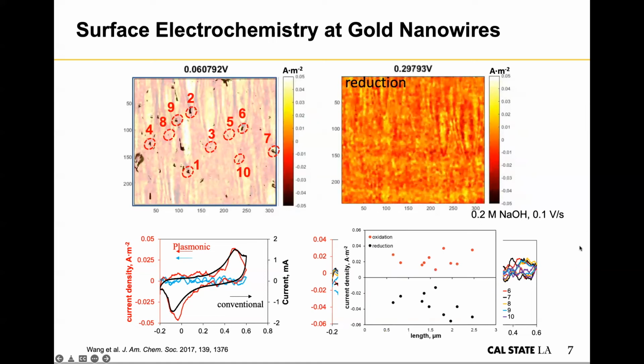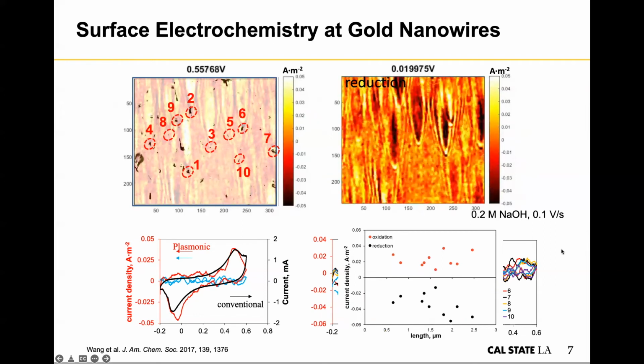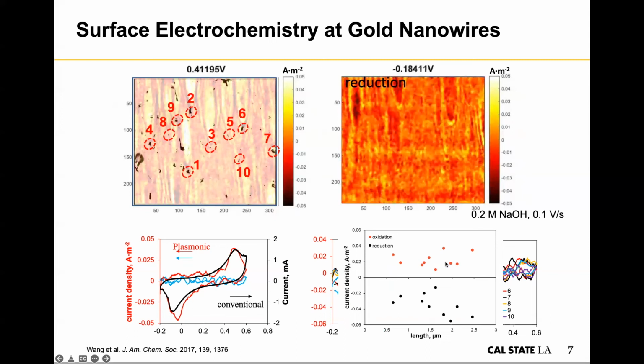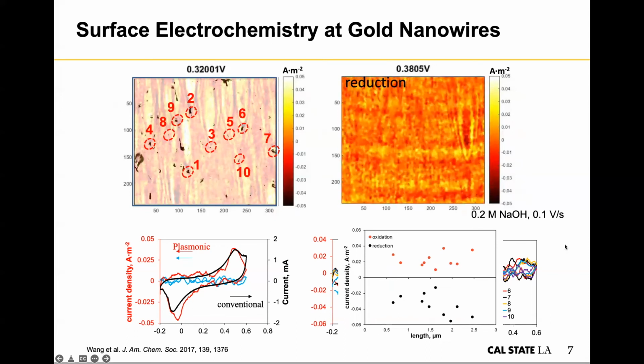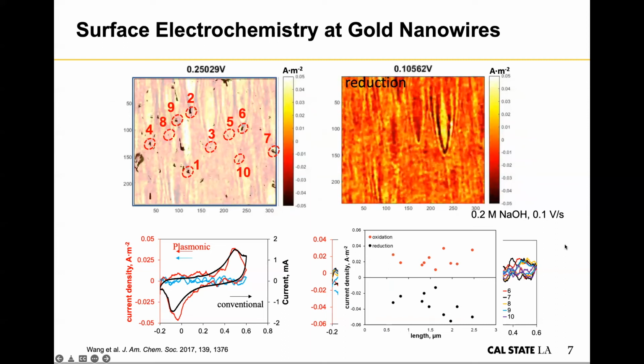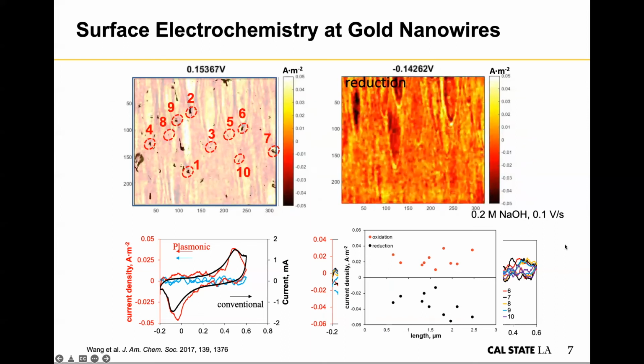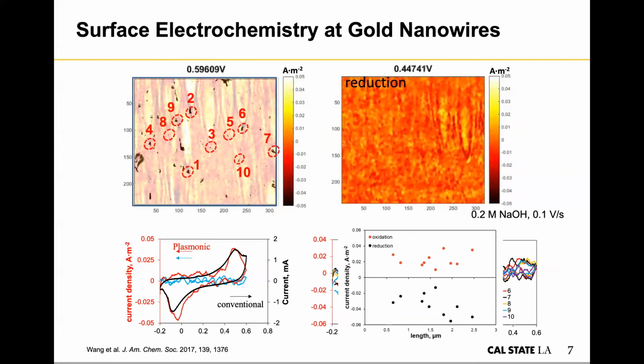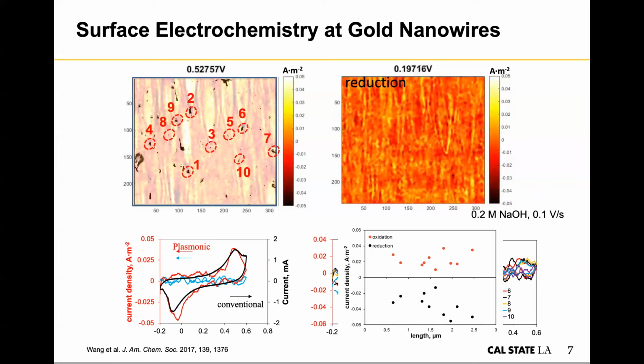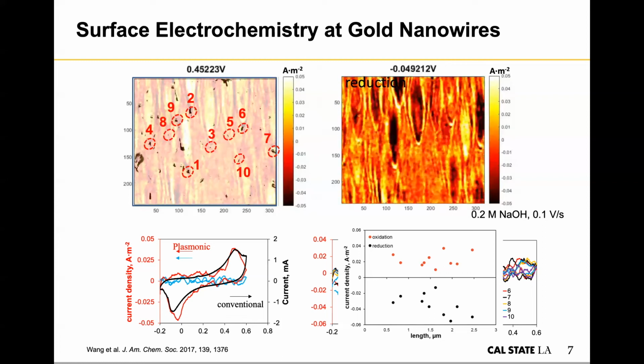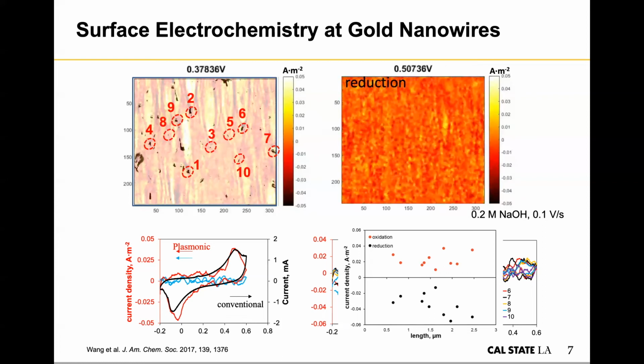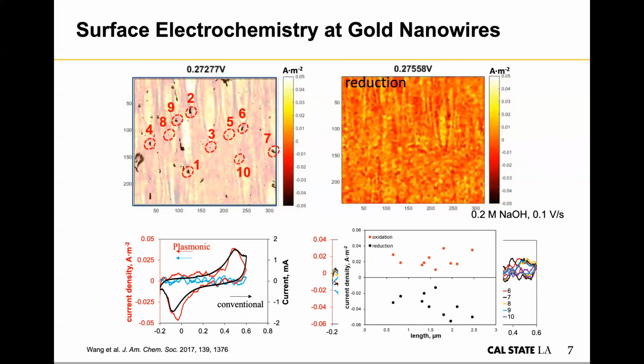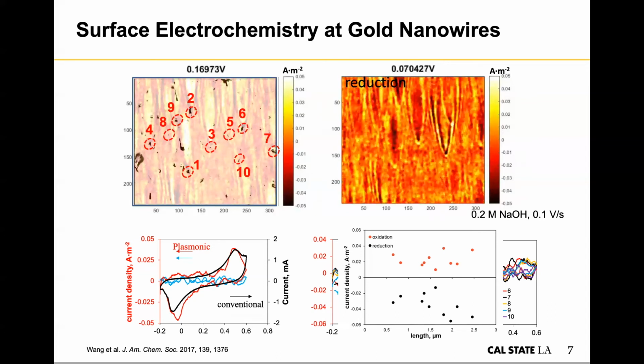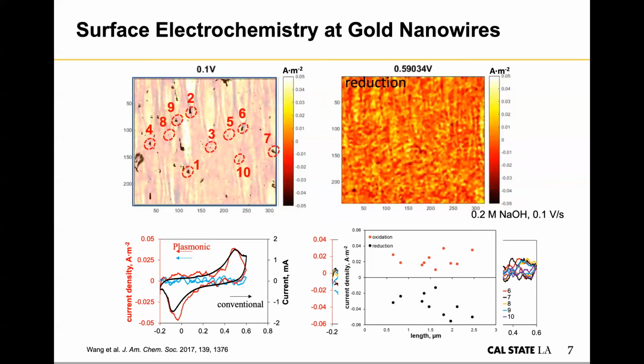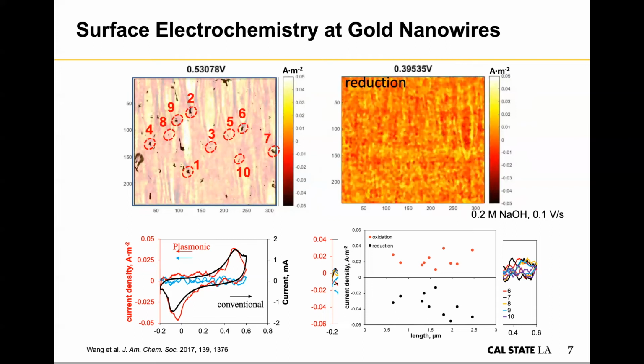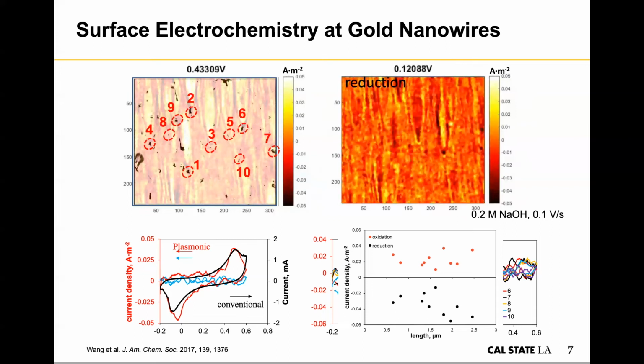We did a little comparison of the intensity among different particles correlating with the size. There's not a clear linear correlation between the size and the signal. Which means that it's not necessarily that when you have a larger particle, you will have a stronger current intensity, which is probably due to the particle surface being covered with some capping layer, which cannot be fully removed during the experiment. So some large particles cannot give you enough electrochemical signals.